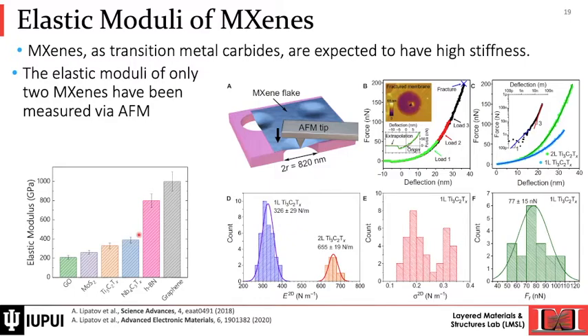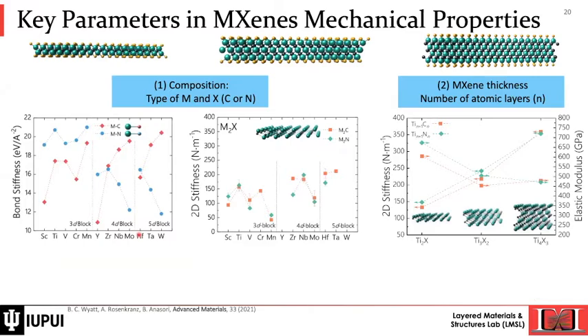Now, what are the key parameters that control the mechanical properties of MXenes? Number one, the composition of MXene. As I mentioned, we have a variety of different compositions, from titanium, vanadium, chromium, yttrium, niobium, to molybdenum, all of these transition metals, and X is carbon or nitrogen. So depending on what composition we choose, even if we know nothing about the mechanical properties, meaning that, as I mentioned, only 2 out of 40 synthesized MXenes have had their elastic modulus measured, how can we understand the other MXenes' mechanical properties? We can simply look at the bond stiffness. How strong the bond of the transition metal with X, with carbon or nitrogen, is in MXene will determine the mechanical properties of MXene.